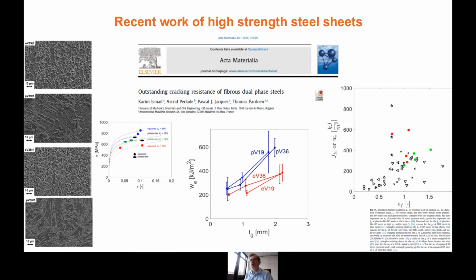Finally, just to show you that we have not stopped working on that. For instance, Karim Ismail did a PhD together with Pascal and with me on advanced dual phase steels, comparing equiaxed microstructure and fibrous microstructure. And Karim did this painful set of tests to measure essential work of fracture at different thicknesses to separate the gamma zero and the work of necking. The goal was to understand why this fibrous dual phase steel was much better than the equiaxed dual phase steel. We wanted to know if it was coming from the necking or from the gamma zero, because that indicates where you have to go to improve even more your microstructure.